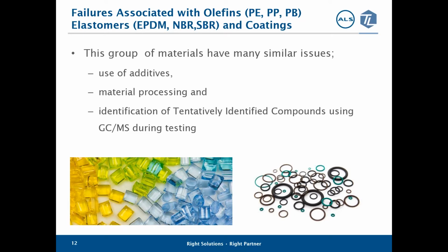In this slide, I've grouped a number of materials together that have a series of common problems because they all have formulations with the same components. All these materials consist of polymers, initiators, terminators, curing agents, antioxidants, and process aids. In addition, they can also contain pigments, antimicrobials, and plasticizers. Not all of these substances become part of the polymer matrix, and the ingredients themselves can contain impurities, degradation products, and hydrolysis products, which can cause failures. In addition, many of the compounds that do extract do not have toxicology data to support a risk assessment. The result is that many of the compounds reported in these material extraction results are compared to an artificially low default pass-fail criteria.